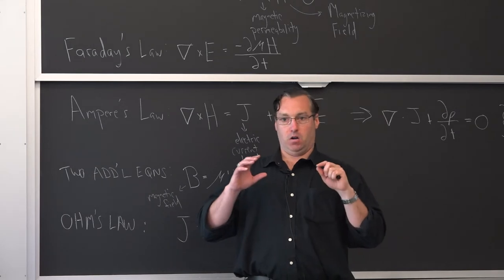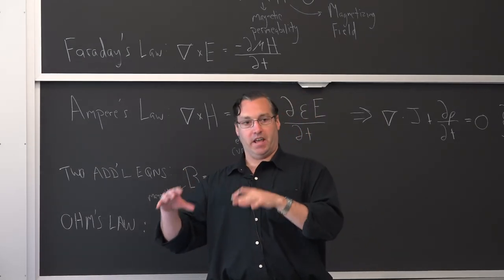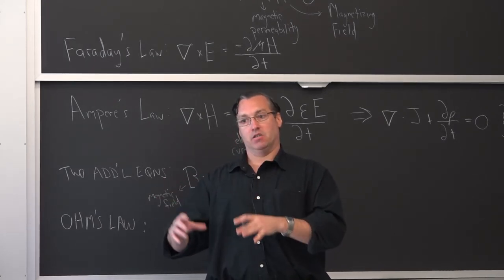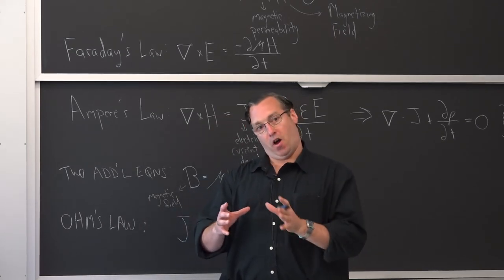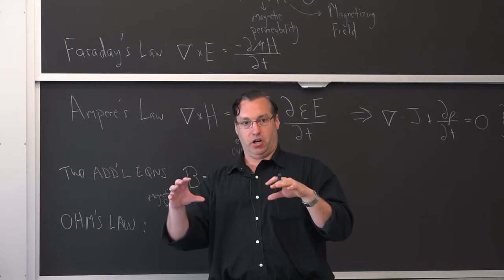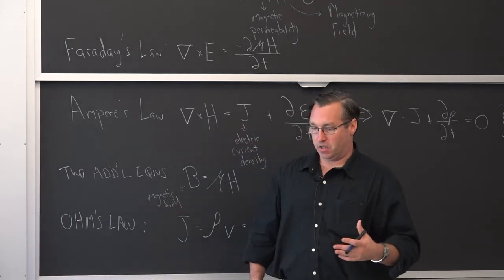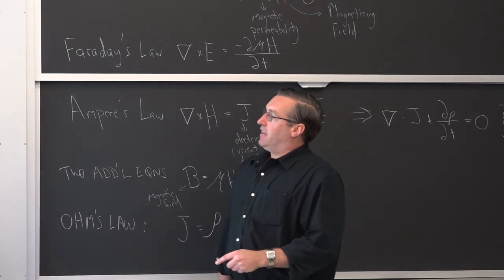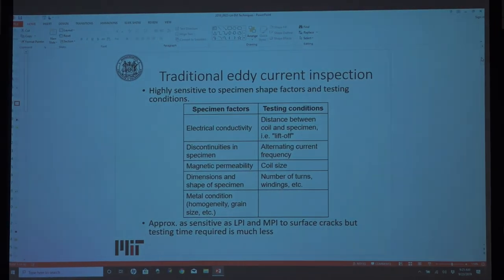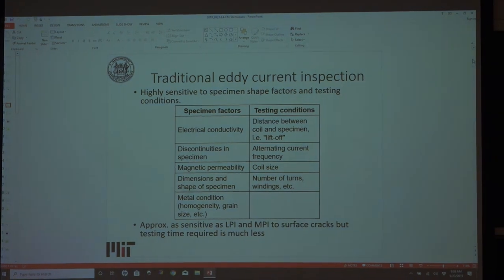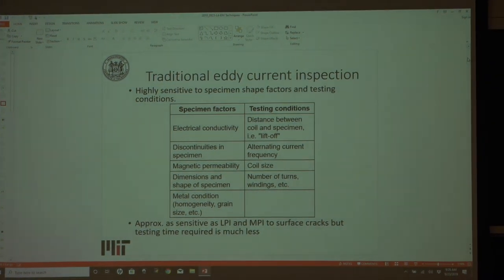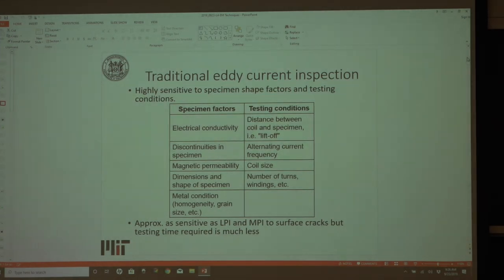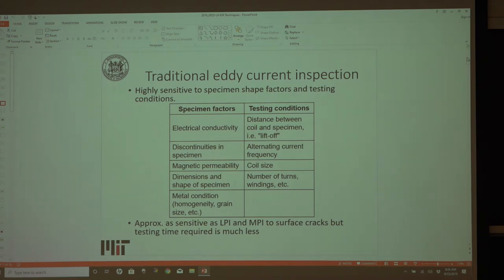If a heat exchanger gets a through-wall hole, the whole unit would need to be removed and replaced — that's downtime at the plant. A rule of thumb is that for a nuclear power plant unit, if it's down one day, it's about $1 million lost per day. This ties into preventive maintenance — you don't want through-wall holes, so being able to plug a heat exchanger tube is very valuable to owner-operators. With respect to sensitivity, the technique is approximately as sensitive as liquid penetrant inspection and magnetic particle inspection, but takes much less time — you can run the eddy current probe in and out of a tube in seconds, versus about 30 minutes for a single liquid penetrant test.